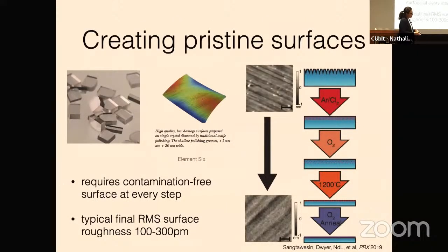So using these kinds of tools for feedback, we could then come up with a somewhat labyrinthine process for creating pristine surfaces in diamond. And again, I'll spare you a lot of the pain of listening to what we had to do, but the general idea is, we start with this state-of-the-art low damage surface polish. We do reactive ion etching to remove the polish damage. That leaves behind a different kind of damage, so we have to remove that with a different sort of etch. That leaves behind its own damage, so we do a thermal anneal to remove this last kind of gentle surface layer. And then finally, we do this oxygen anneal to make a chemically nice surface.